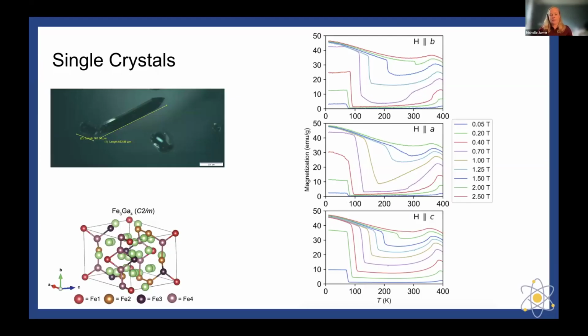Whereas you increase the magnetic field, when we go from low field to high field, we're actually suppressing the transition. So as you can see at low field, or low temperature, we have this metamagnetic transition that actually increases whenever we apply more magnetic field. And then in the upper range, around 360 Kelvin, we have the secondary magnetic transition that is actually being suppressed as we increase the field.